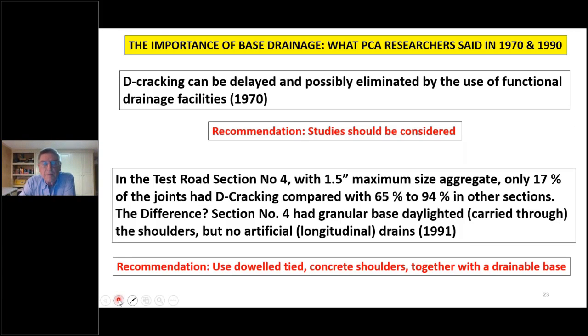Base drainage: the researchers back then said that the decracking can be delayed possibly by the use of drainage facilities. They should be considered, again, recognizing the root cause. They also had test section number 4 out of 105 test sections where the maximum aggregate size was 1.5 inches, and they had what they called a daylighted granular base, so it carried through the shoulders. So there was base drainage there. That particular one had 17% decracking in the joints versus 65 to 94 in all the others.